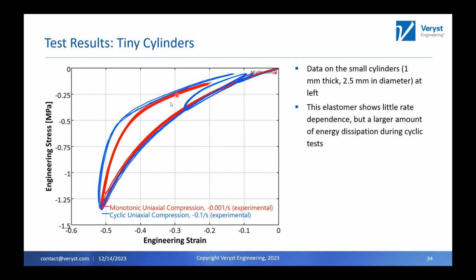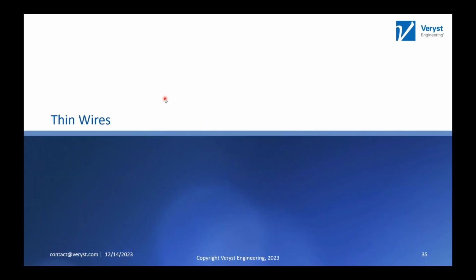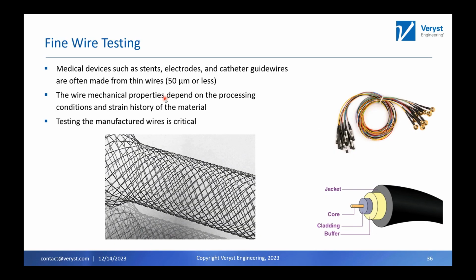So you can see here, the test data though is very clean, very repeatable. Again, we tested at 2 rates. This blue color was at 2 decades higher. We don't see a lot more difference in the stiffness, but we do see a difference in the unloading and the hysteretic behavior of these materials tested at 2 rates. Excuse me. And I think our last example is testing thin wires.